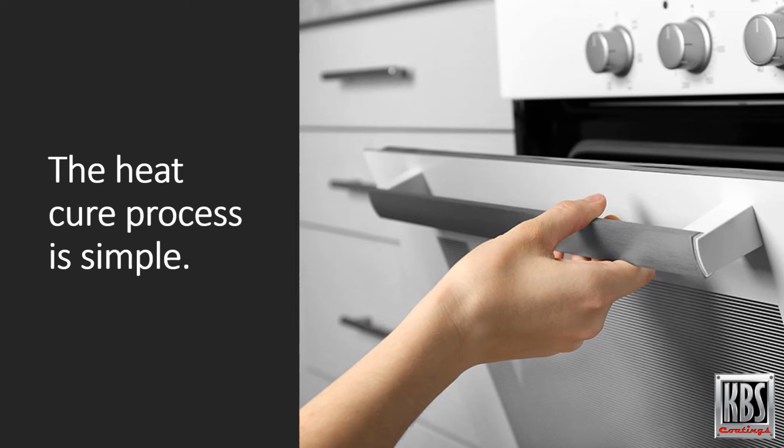The heat cure process is simple. You can bake the parts in an oven or on a grill at 350 degrees for 20 or 30 minutes. Or, after the parts are installed, start the bike and let it idle. As soon as you see the XTC start to smoke, turn the engine off and let it return to room temperature. Repeat 2 more times. After you've done that, start the bike and let it idle until all the smoke dissipates from the XTC. This means you now have a complete heat cure. Let the bike come back to room temperature.